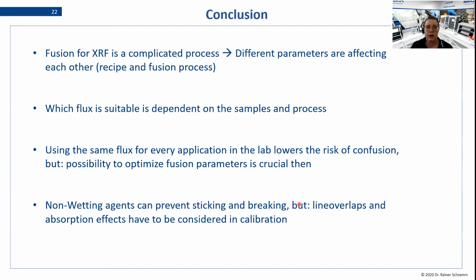And then last but not least, it's the non-wetting agents, and they can prevent the sticking and breaking, but please be careful. The line overlaps and the absorption effects, they are real, and you have to consider them in your calibration. So all in all, you have these three things that you have to take care of. You need the suitable flux, you use additives whenever necessary and not when they are not necessary, and then you need a good fusion technique, and then you will be fine. Then the beads will come out just as you expect them.